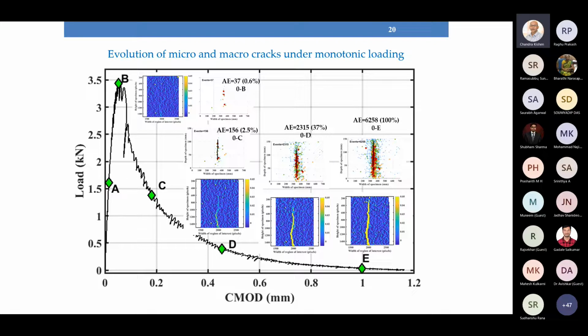Now at the point C, that is in the post-peak response, approximately 50% of the load has come down. We have seen on the surface through digital image the major crack, and also we see about 2.5% of the events which have formed. And continuing, at point D, we see that nearly 37% of the events have been formed, and at E, where final failure occurs, 6,258 events have occurred.